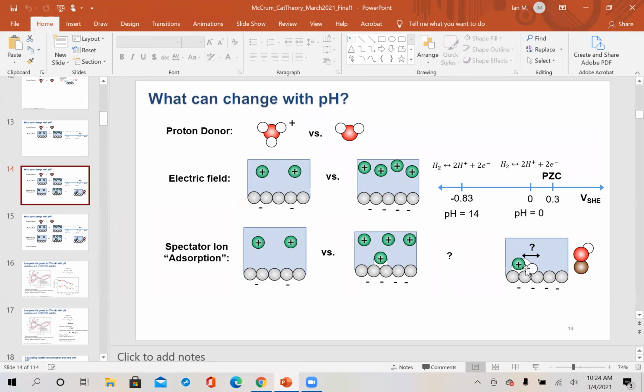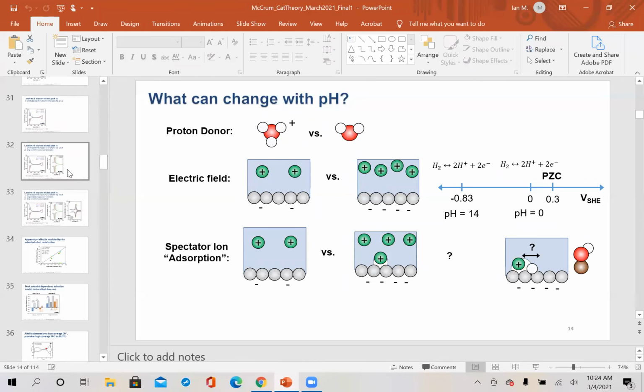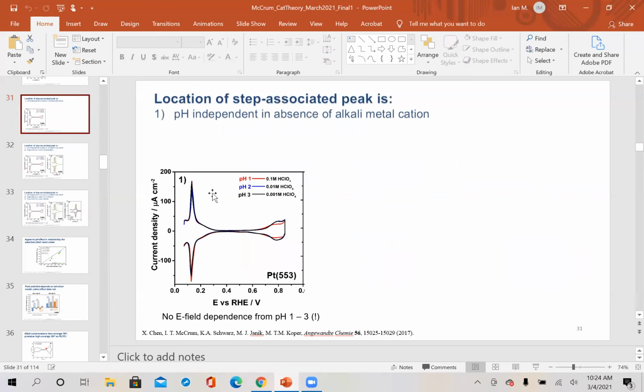To differentiate it from the field effect, I would say it's really this local 3D field effect, as opposed to just the 1D or 2D field across the surface. We consider that because we know if we change the pH without a cation, the peak does not shift. When we change pH without the cation, we're still changing the electric field across the surface. But at least over this pH range, over some small range of changing electric field, we do not affect the binding of hydrogen and hydroxide in water on the step. It doesn't shift. So this is why we're viewing this effect of the cation as somehow slightly different from just the 2D field effect.